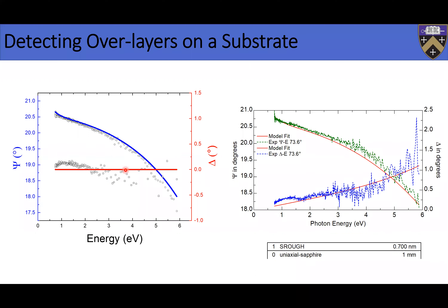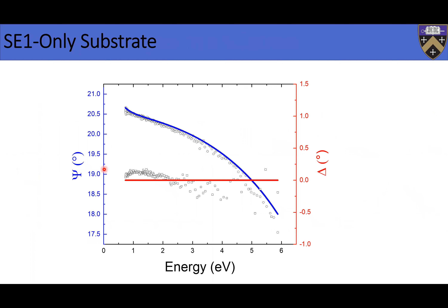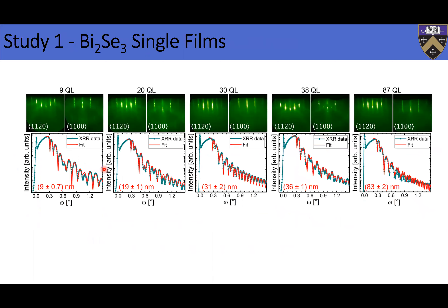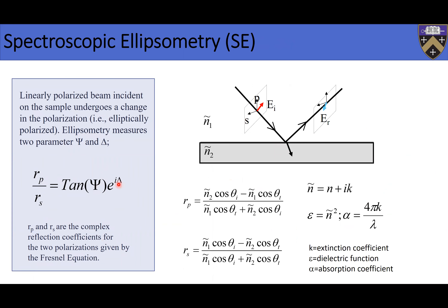Let me go back to give you an idea. The delta is zero — and the question is why. Sapphire is transparent in this spectral range, so K is zero. That means the Fresnel coefficients are no longer complex numbers — they are real numbers. The ratio is also real, and therefore delta has to be zero. So if you don't have delta equal to zero — like in this left-hand spectrum — there's a small problem.